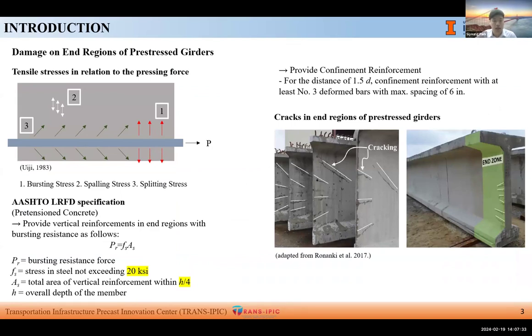To overcome this, AASHTO LRFD specified requirements for vertical reinforcements and confinement reinforcements. It is highlighted that stress in steel within a length of height divided by 4 be less than 20 KSI. However, even with securing this specification, we can still see inclined and horizontal cracks in the end region of pre-stressed girders.